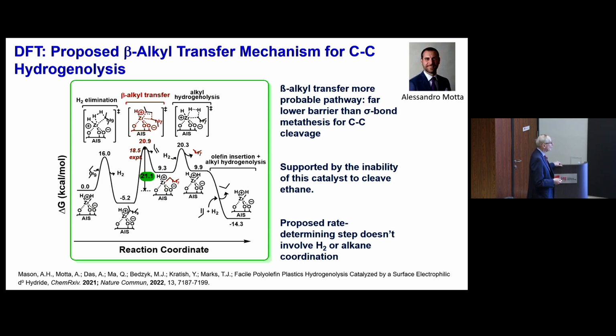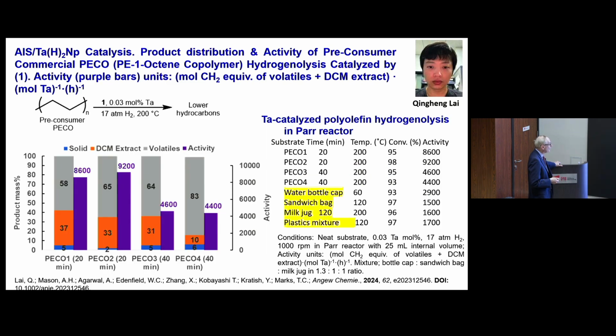And then the question is, so the beta alkyl transfer is the highest hump on the reaction surface, and that's the turnover limiting step. So Qingheng then wondered, what about tantalum? So that's on the next column of the periodic table, and it works fine. It's probably a little more thermally stable, and this just has to do with his methodology for separating the waxes, the gases, and then of course we need to quantitate the yield and what's called mass balance, and that works out pretty well.